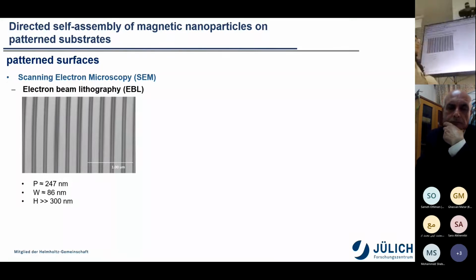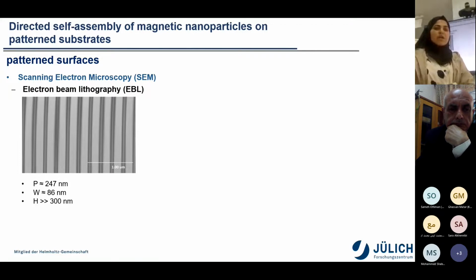Here I use magnetic assemblies. It's grating lines of silicon, and it plays a major role in this part of my work. Therefore, I will show the results of the characterization of these samples. They were produced by electron beam lithography in collaboration with the Helmholtz Nanoelectronic Facilities at Forschungszentrum Jülich, and we end up with grating grooves with a width of less than 100 nanometers.